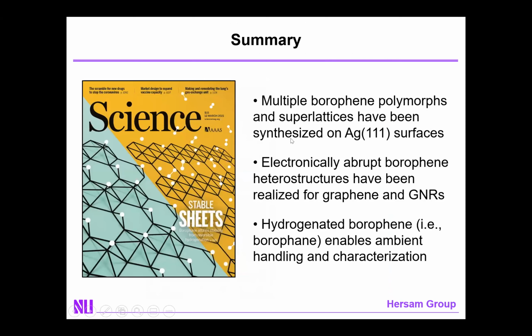And as a result, let me conclude there. I'm sure I'm out of time. I tried to make three points today. One is that multiple borophene polymorphs and superlattices can be synthesized on silver (111) surfaces. You can also realize electronic heterostructures for both graphene and graphene nanoribbons. And hydrogenation, we believe, is now the pathway to getting this material out of UHV into ambient conditions, which is going to, we believe, accelerate its use in a wide variety of applications.